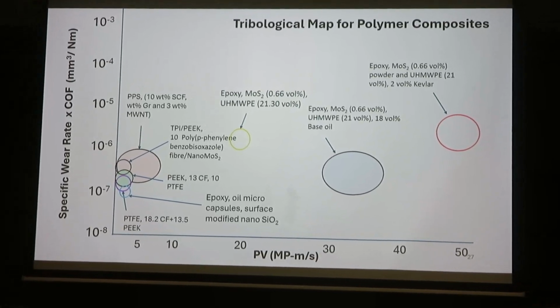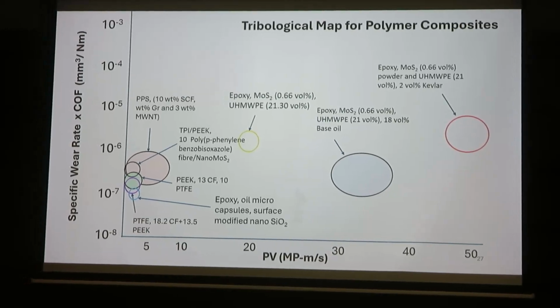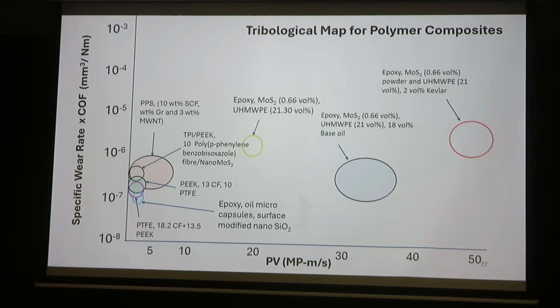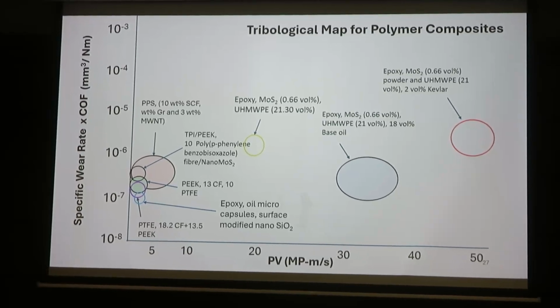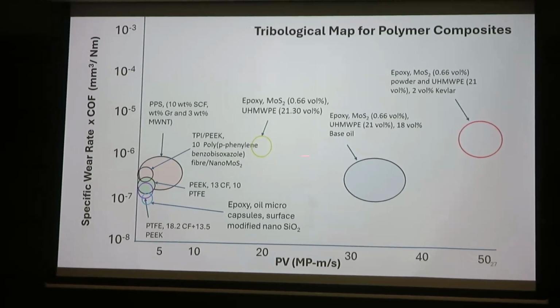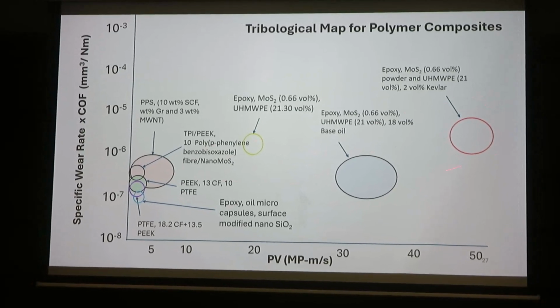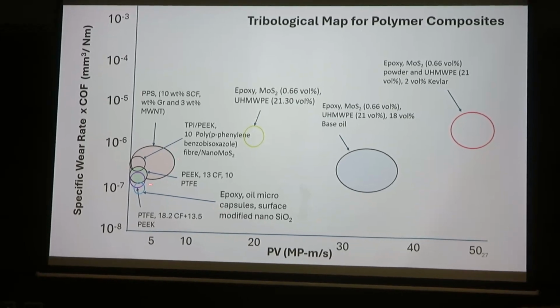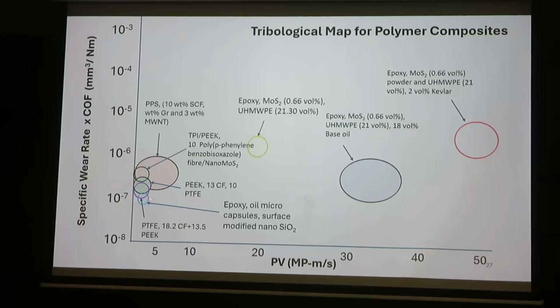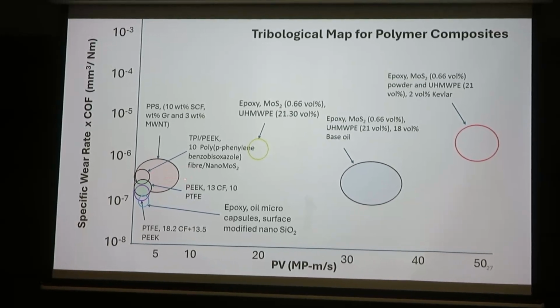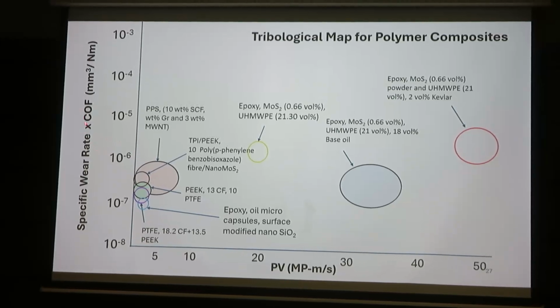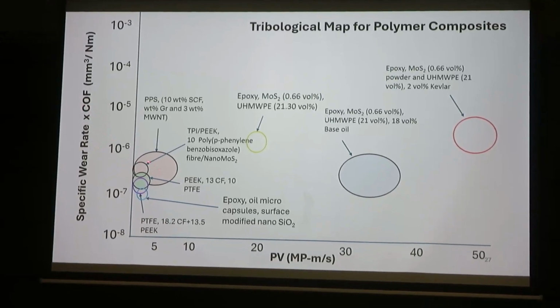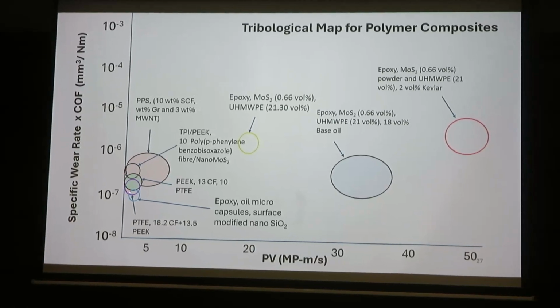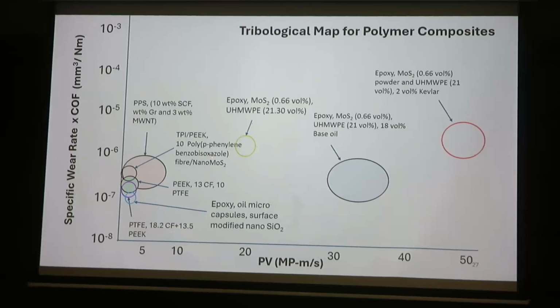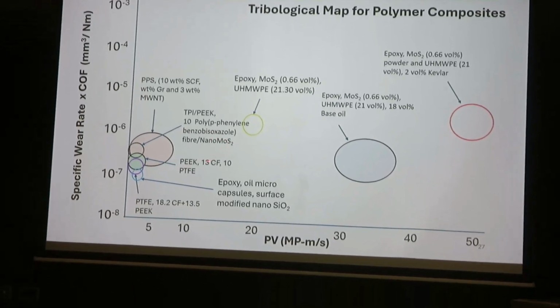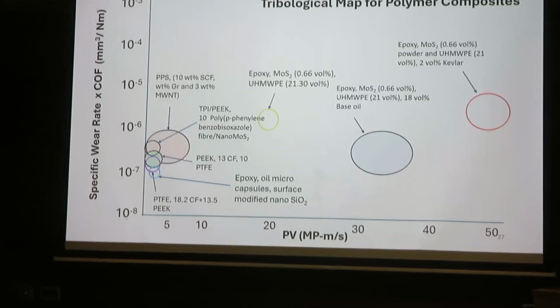So if you are trying to make high performance polymer composites, it is better to compare their PV. Of course, comparing load and speeds is also important. And here, these are all literature values and these are our values. Actually, most of the time you will see that the literature is around here, so that means PV factor of 5 or less. And this is multiplied by coefficient of friction here, so this is in the range of 10 to the power minus 7 to 10 to the power minus 6. These are good polymer composites that have been made for tribological applications.